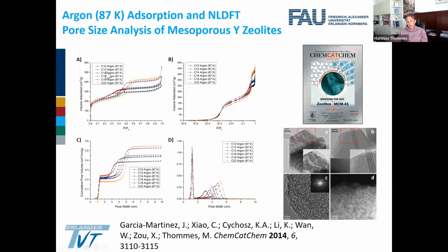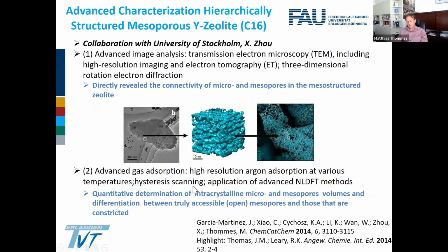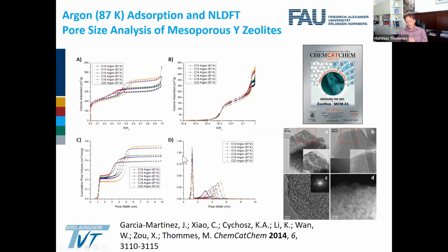Okay, and you see here, when you go to larger lengths of surfactants, it's a typical MCM-41 synthesis. Then you see here how the mesoporosity becomes larger while the microporosity stays the same. So we take one of these samples out, and then we coupled this approach with world-class electron microscopy and tomography. And with this, we could show that indeed these mesopores and the micropores are really connected in a hierarchical way, meso to micropores,